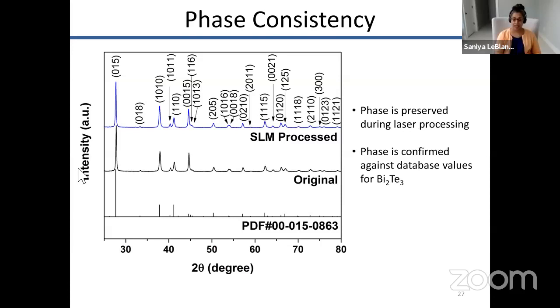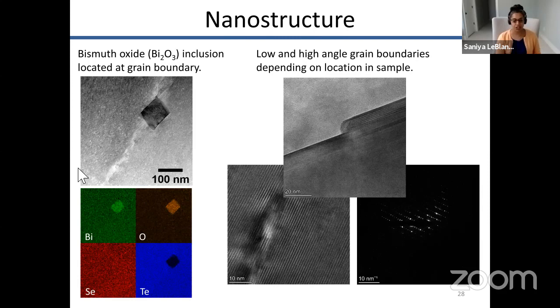And so that leads us to having to look at the nanostructure. There's something in the nanostructuring of the material that happens when you laser process it that must be impacting the transport properties. And what we have found in our preliminary work in characterizing the nanostructure is that you can't pick it up on X-ray diffraction, but if you look at the material with a transmission electron microscope, you can see that there are indeed these oxide inclusions, these bismuth oxide inclusions that form in the material. The density is low enough that you don't pick it up on X-ray diffraction, but they are indeed there, and the presence of them is enough to actually change transport of carriers.